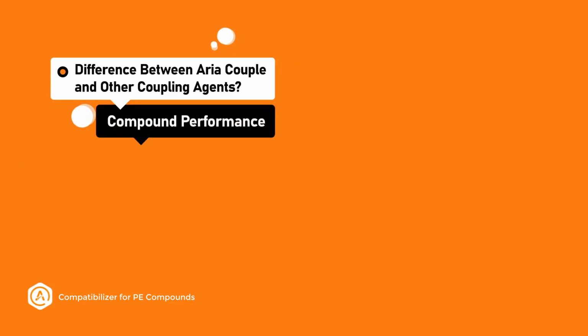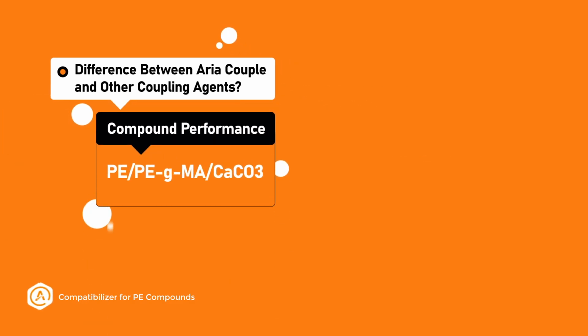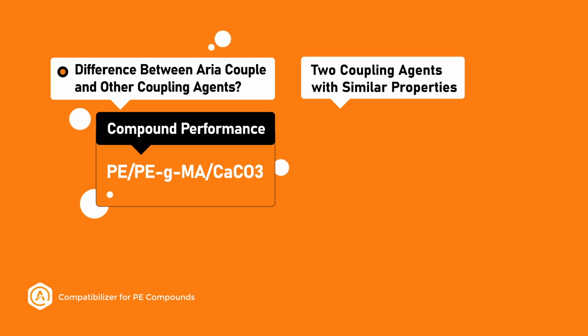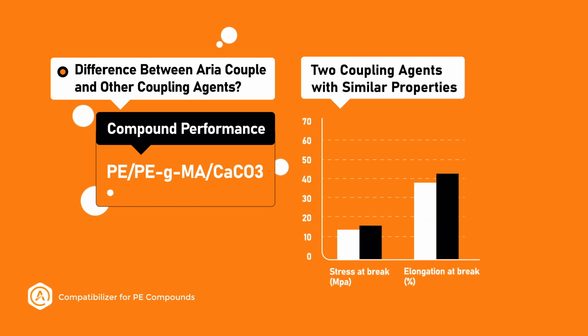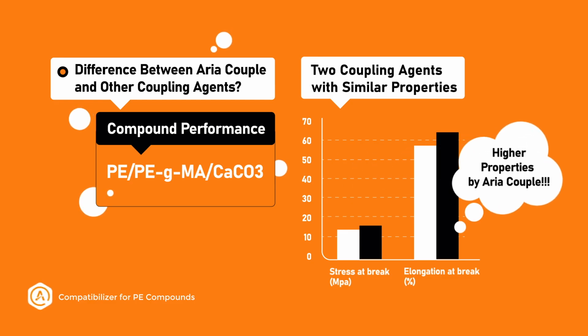To compare their efficiency, performance, and effect of coupling agents in particular compounds of polyethylene with calcium carbonate filler, the two previously mentioned grades were examined. Tensile and elongation characteristics of polyethylene filled with calcium carbonate have higher value by means of Aria couple 1196 as a maleated polyethylene coupling agent.